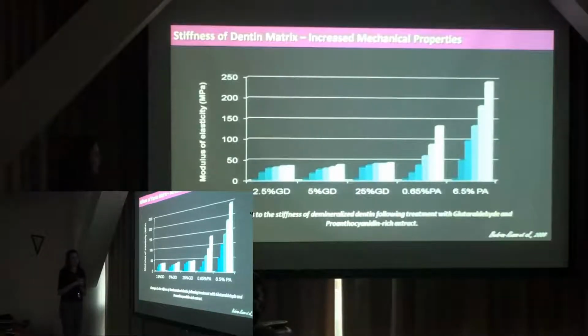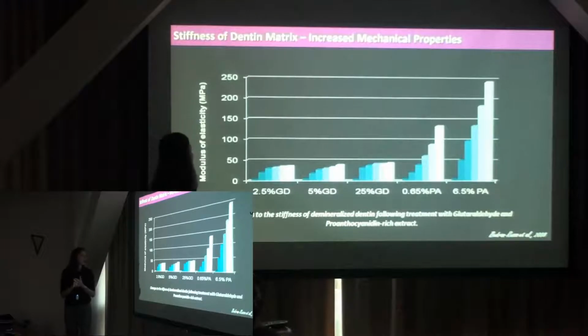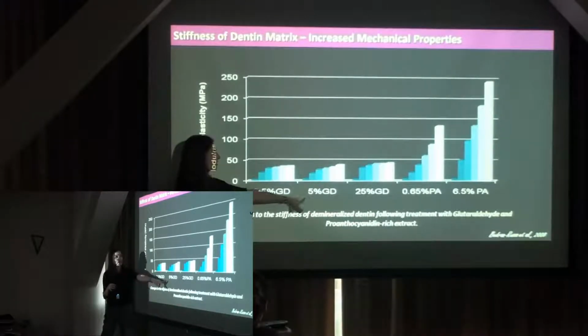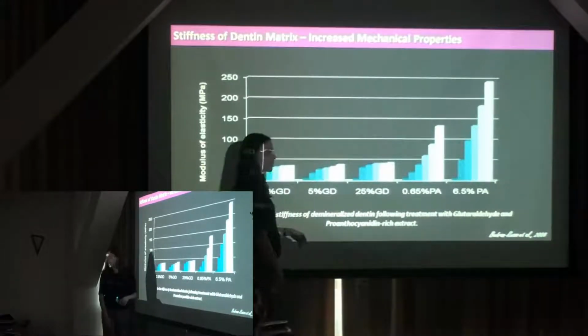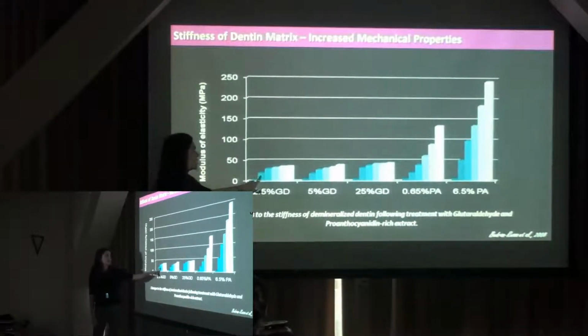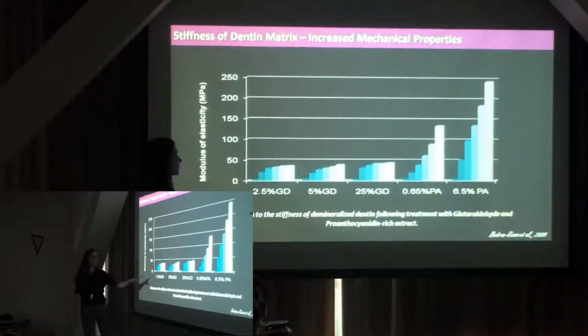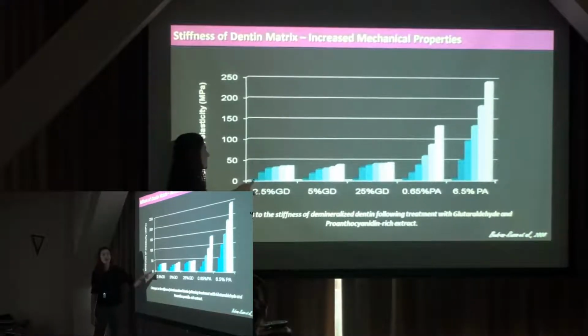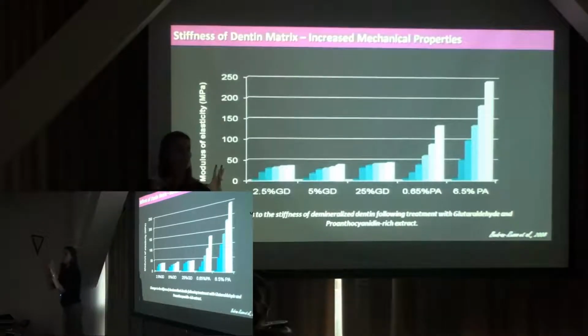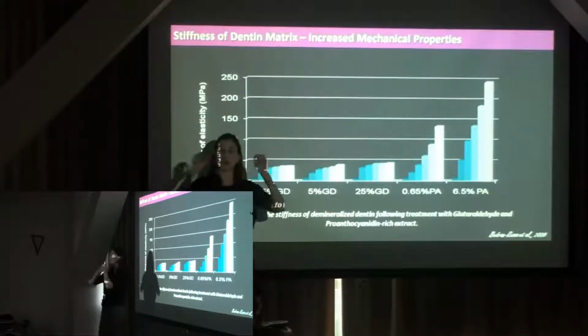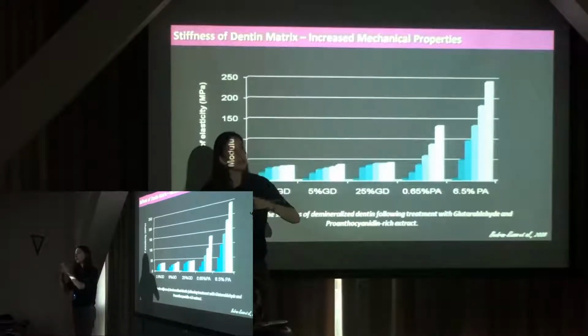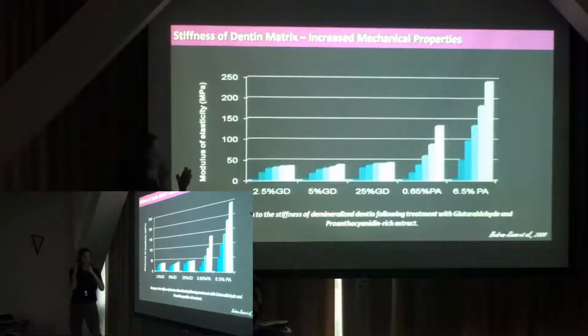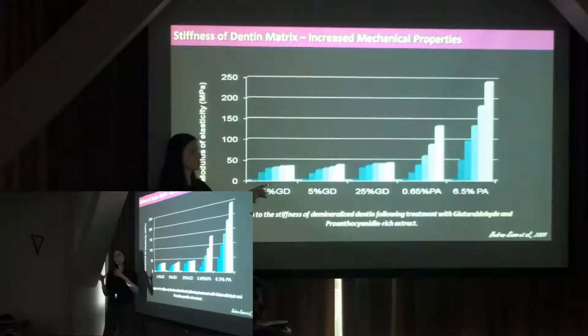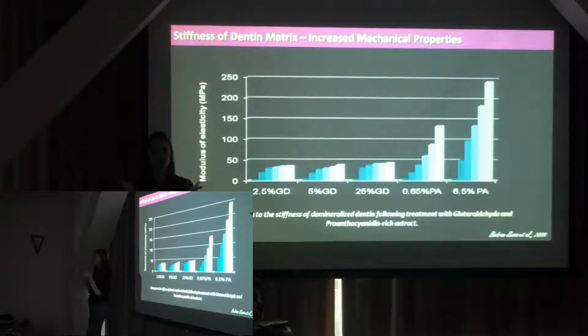So this is the first study, the second study that we published, in which we had glutaraldehyde in different concentrations, and we had these proanthocyanidins from grapeseed extract. And what you can see, we had here a time dependent, and I'm sorry because I forgot to put it in, but basically we have baseline. So the baseline, if you cut a piece, what we do is that we cut a rectangular shape of dentin, we decalcify it, so we have only the extracellular matrix there, and we put it in the solutions, and we use a flexural model,